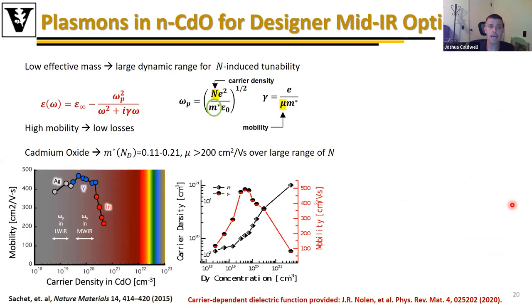All right. So why cadmium oxide? Well, if I look at a plasmonic medium, right, the dispersion is dictated by the Drude formalism, right? Here I can look at this plasma frequency and find it's dictated by the carrier density, but how well I can tune this plasma frequency with carrier density is dictated by the magnitude of my effective mass, right? And it turns out, because of the Moss-Burstein effect, as I change the carrier density, the effective mass of the free electrons in the material actually changes from about 0.11 to about 0.21. Furthermore, which gives us a broad spectral tunability of the plasmonic resonance or the plasma frequency.